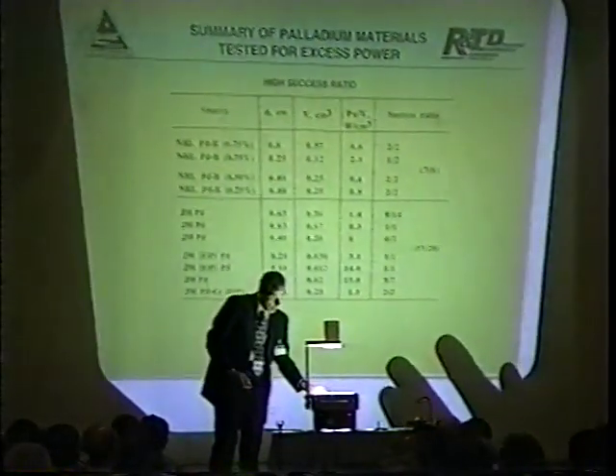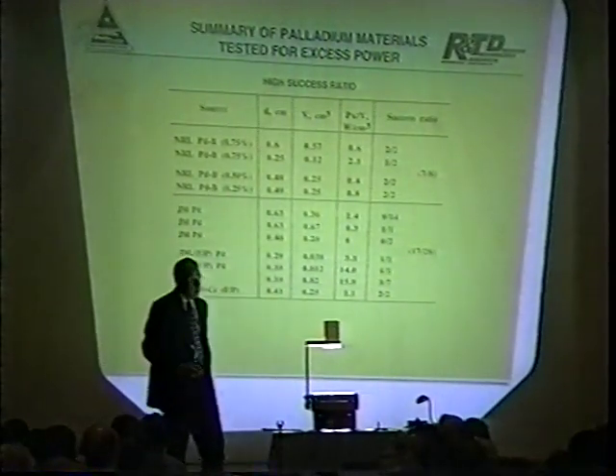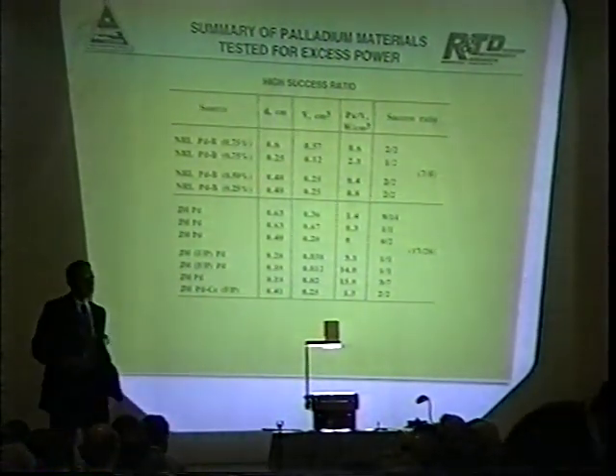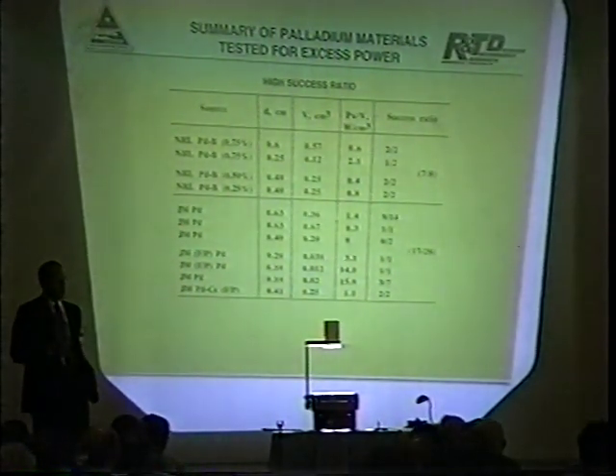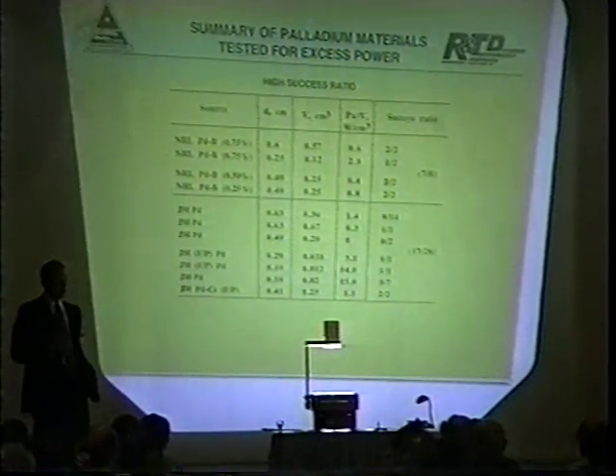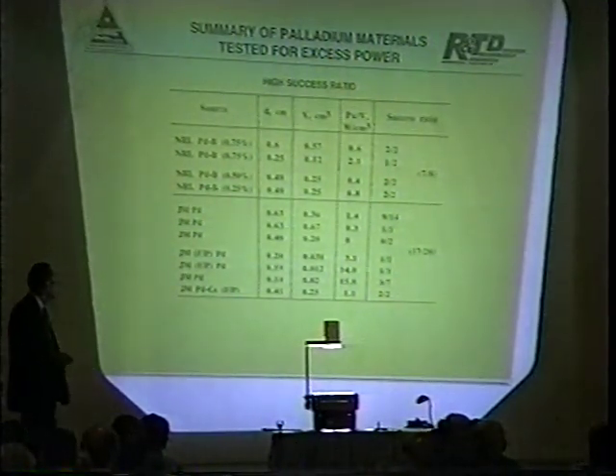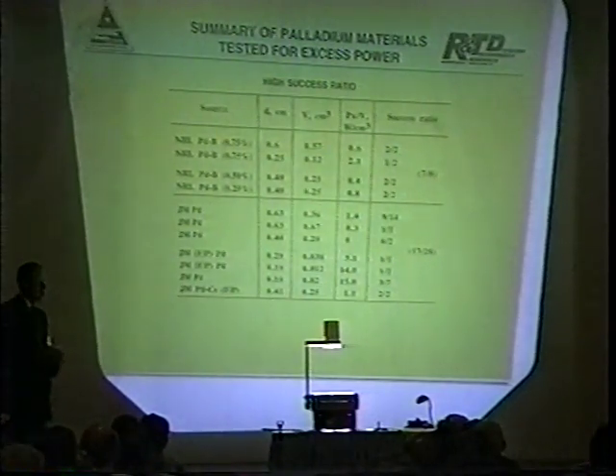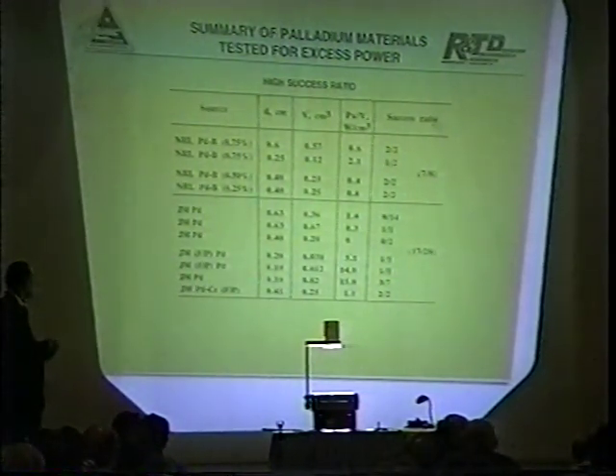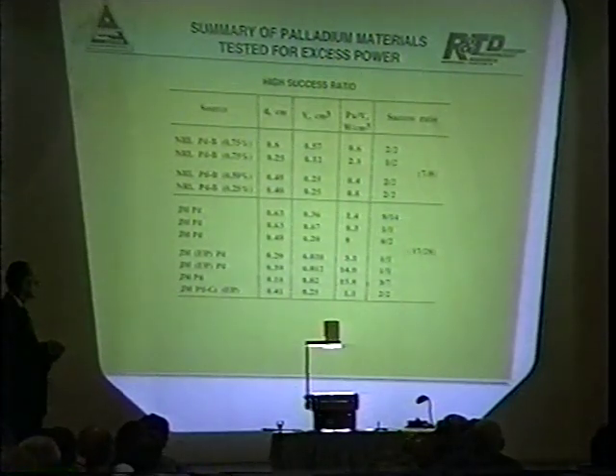In concluding, I want to show our success ratio of all the experiments that we ran, the ones that have excess heat. We find there's a definite grouping. The palladium boron material made by NRL is our most successful grouping. 7 out of 8 produced excess heat.